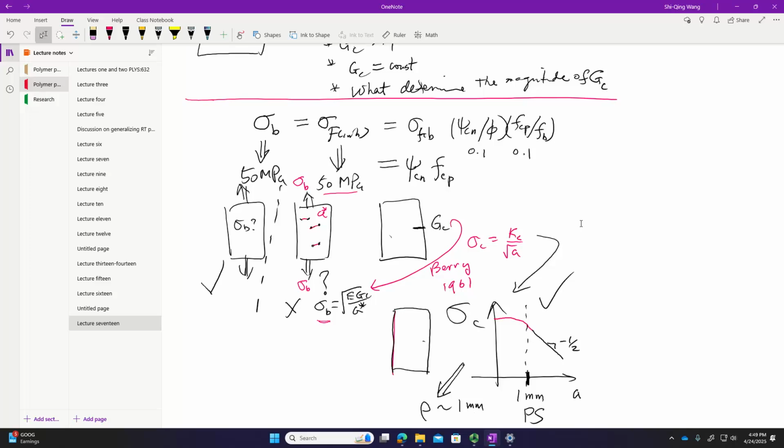That if you have a piece of brittle, glassy polymer, go ahead, make a big enough cut, you will get Griffith's. That doesn't contradict anything like GC being much larger than gamma. That's a totally separate question, right? That you understand. And we also talk about why GC is much larger than gamma, because rho is so large.